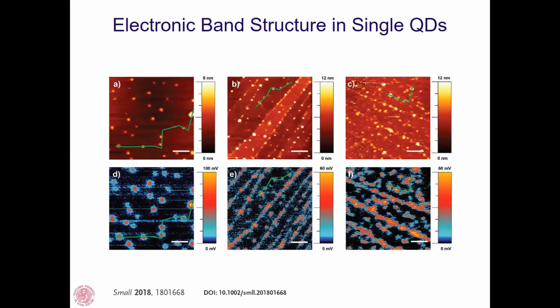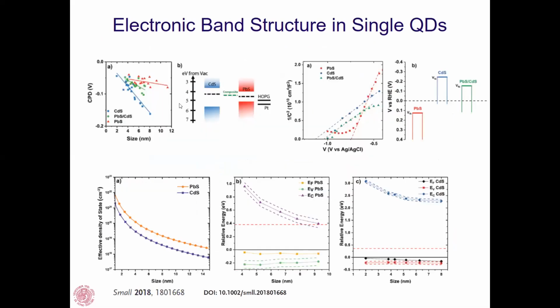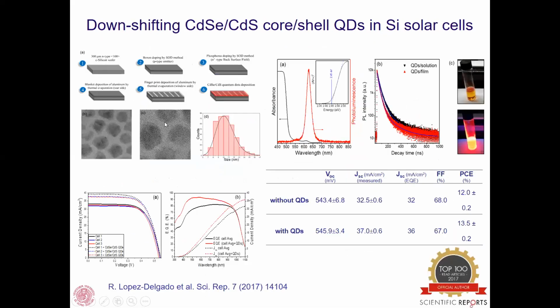And here are the topography and Kelvin probe measurements. As you can see, let me put attention only on the first left panel. You see that different compositions for cadmium sulfide, lead sulfide, and the composite system are consistent with the decrease of contact potential difference with the size. And then we come to application of these materials.